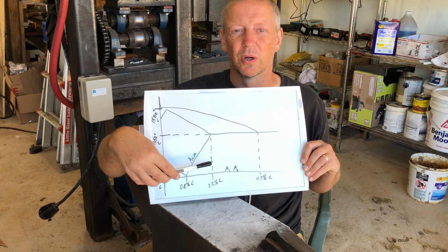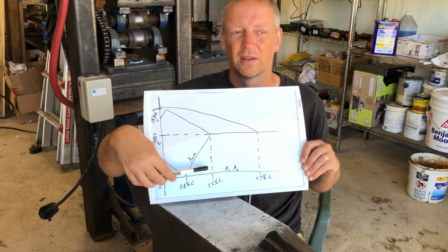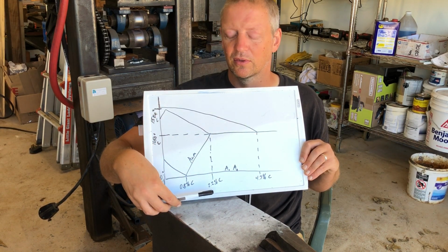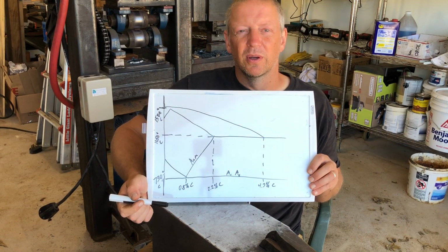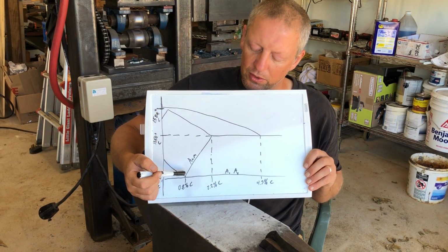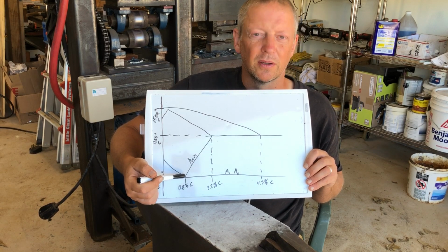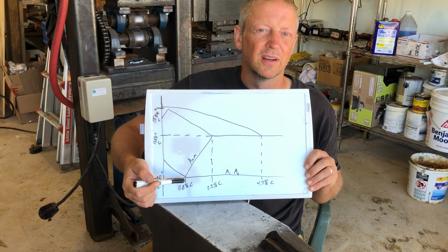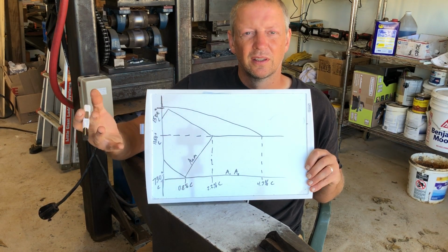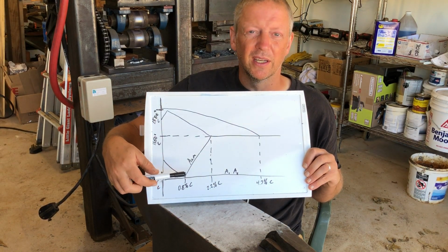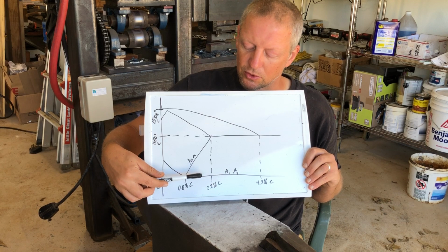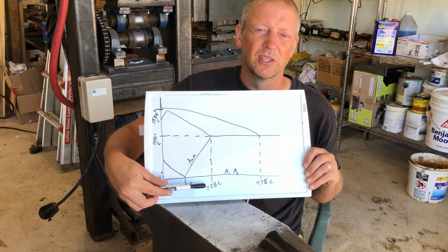You can more readily witness it in the cooling process, in which you get what's sometimes referred to as recalescence, where as you are cooling, you start to approach this transformation, and the steel actually releases energy, which you see in the form of light, or a brightening of the steel, as it cools and that transformation occurs.